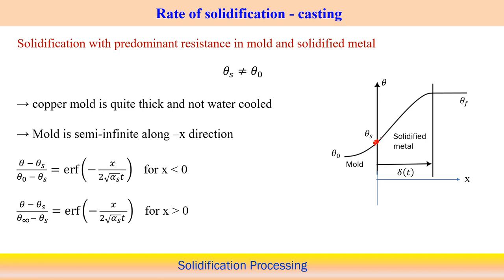So earlier we started with the temperature at the mold metal interface being theta S, and some temperature gradient reaching theta F over the solidified metal. But initially we assumed that theta S equals theta 0, that means there is no temperature gradient. Here we can assume that theta 0 is different from theta S, even theta 0 is lower than theta S. So it means that over this mold wall some temperature gradient also exists. Now how to incorporate this temperature gradient? There are two resistances, one is this part, another is this part. These two thermal resistances have to be incorporated in this particular equation, and here we can incorporate the heat contact resistance at the two different interfaces.